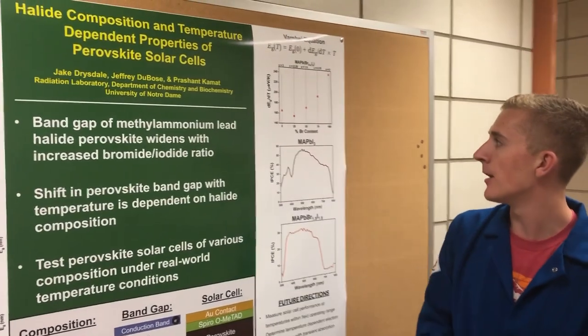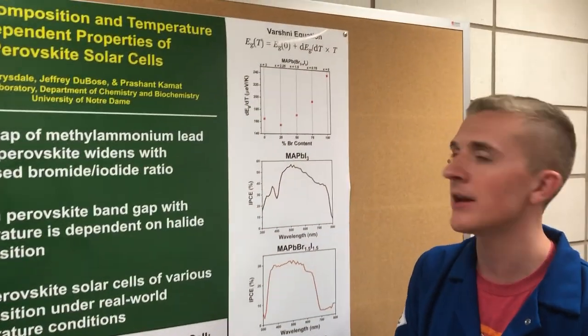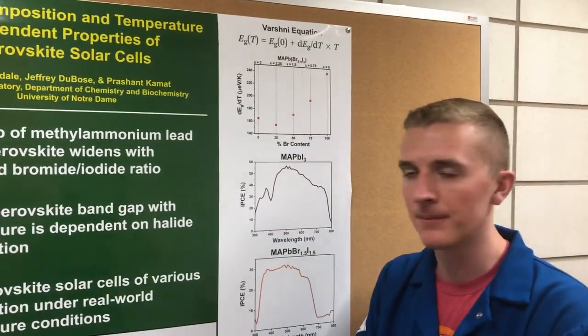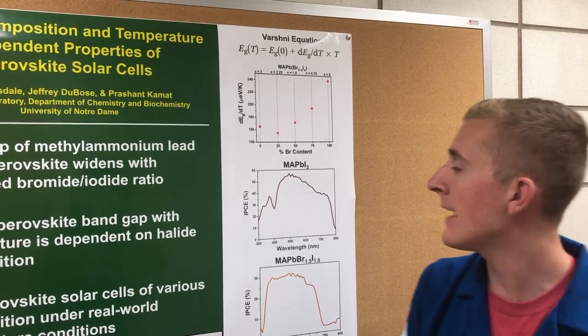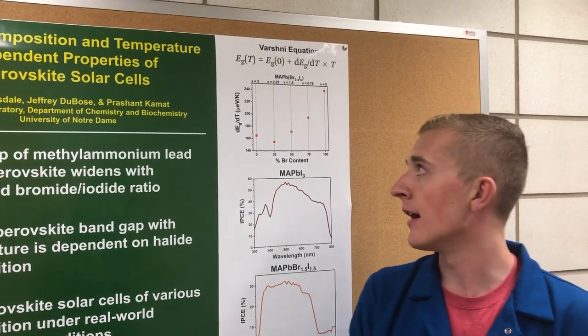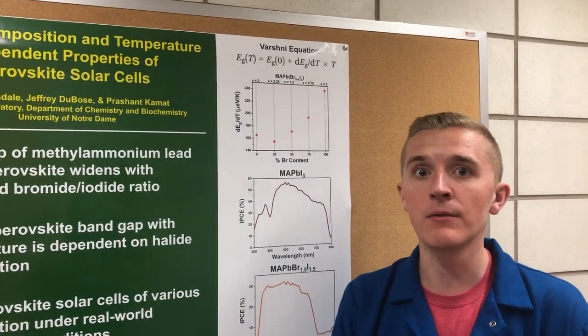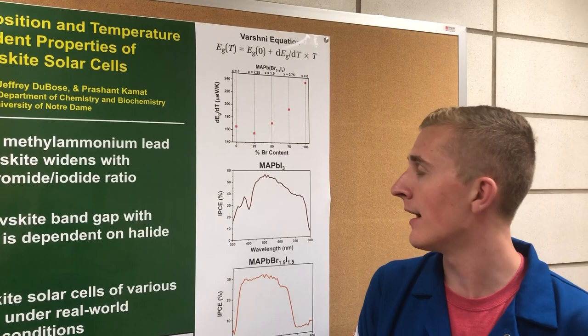As we can see, from a bromide content of about 25% to 100%, the bandgap increases more quickly with temperature with more bromide content.